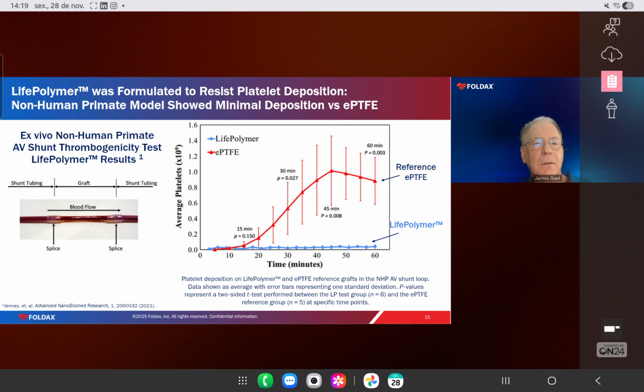But the takeaway message is that on the y-axis is the average platelet content on the material, in billions. It's just a linear scale. And then the time in minutes, so it's a relatively short duration experiment. The baseline material, which is known to be quite biocompatible and is the kind of standard material that does not have much platelet deposition, is expanded polytetrafluoroethylene, so expanded Teflon. It's basically stretched Teflon, which is porous.